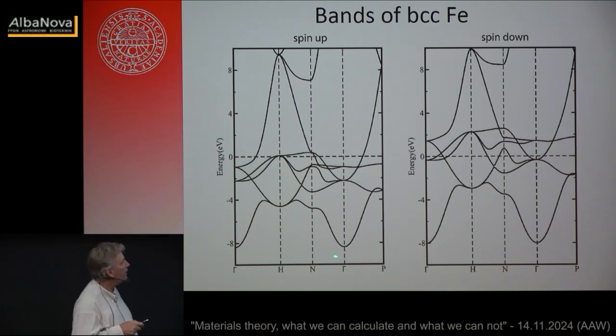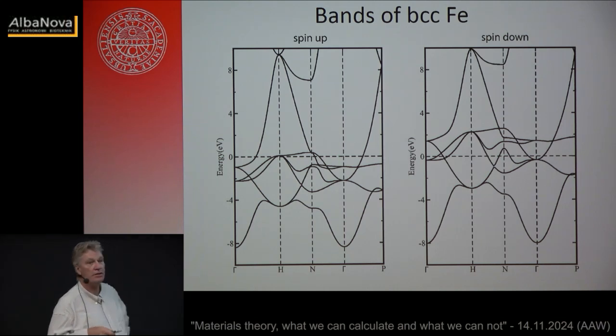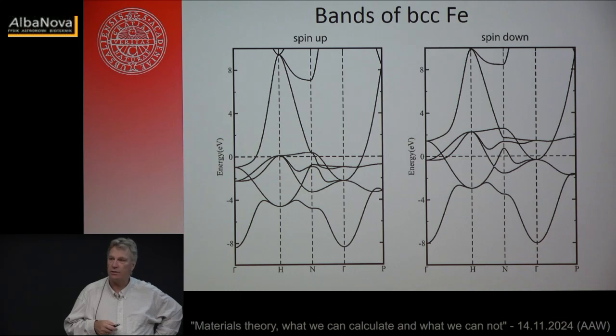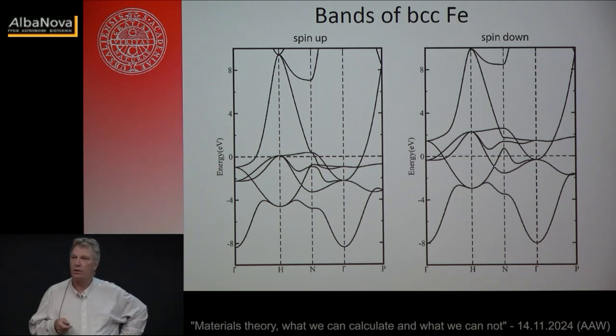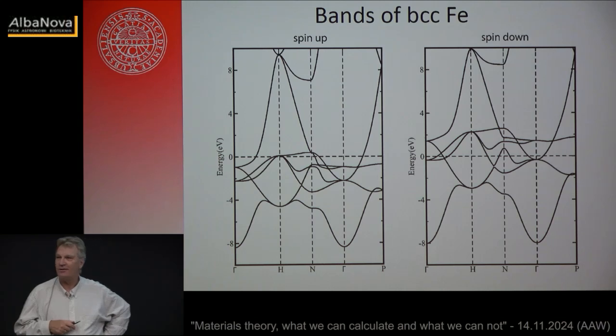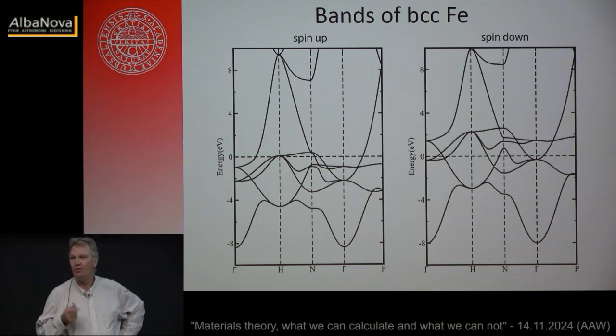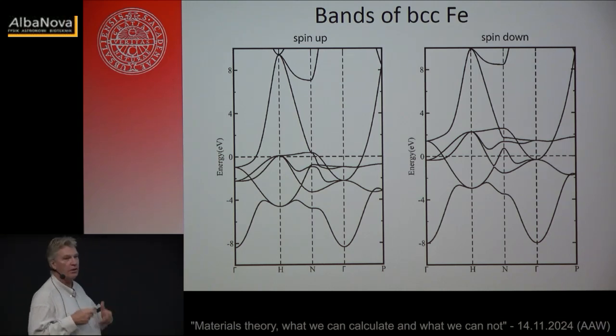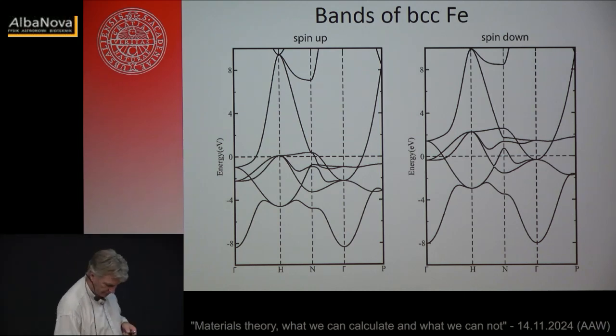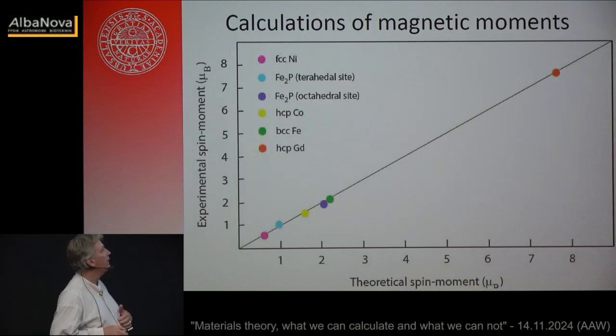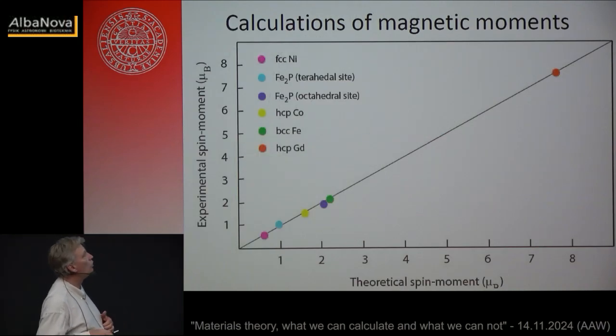So one can fill up electron states in spin up and spin down up to the common Fermi level, and you say, okay, I know that the electron g factor is 2 in our world, and 2.00189, whatever, in the real world, but in our world it's 2, and then you can deduce what the magnetic moment is of this material. And if I now make a plot of calculated and measured magnetic moments over a range of materials, it looks like this.